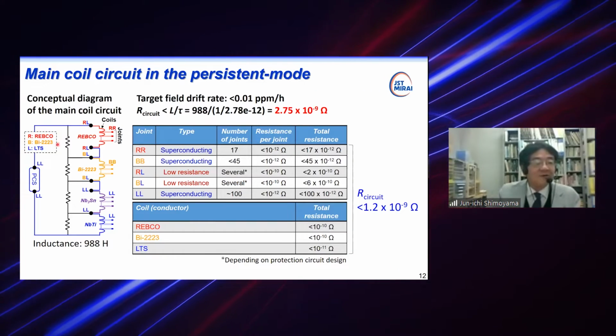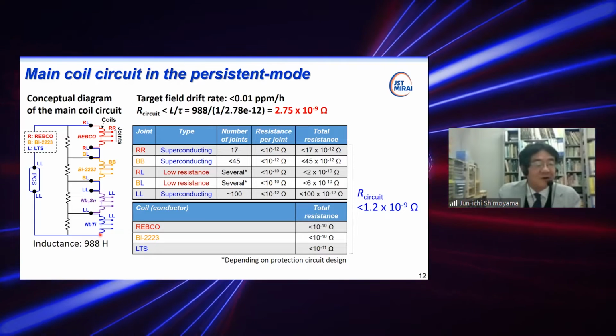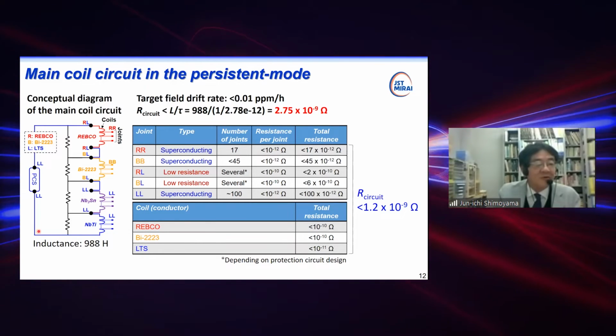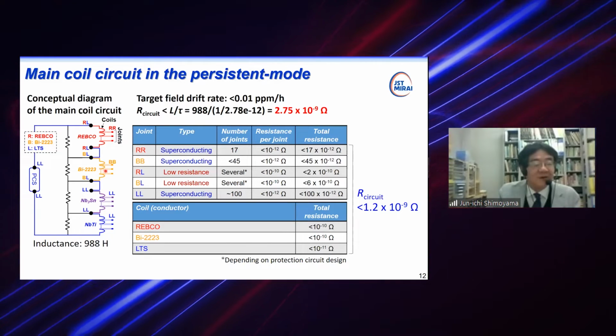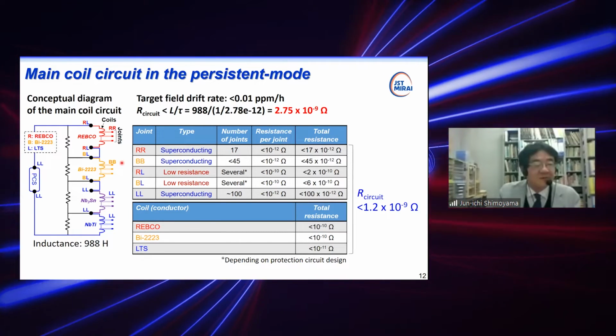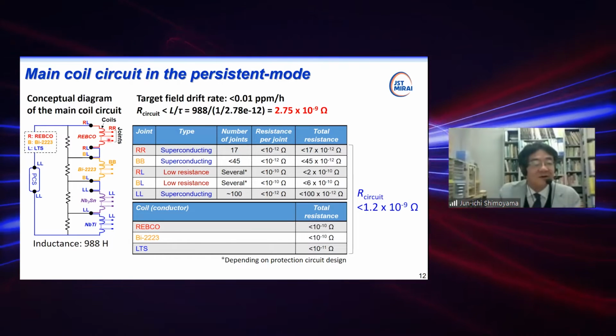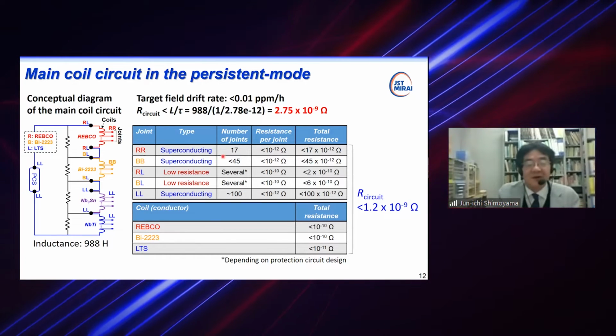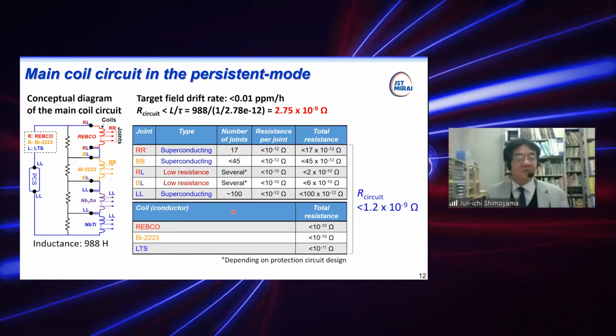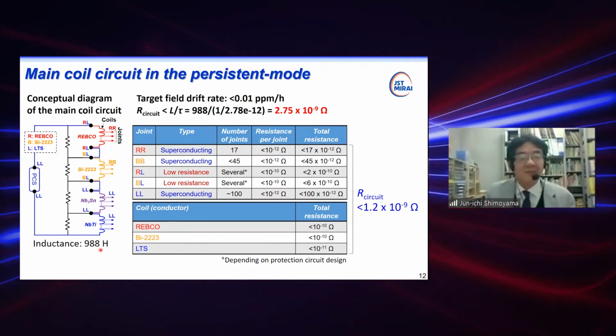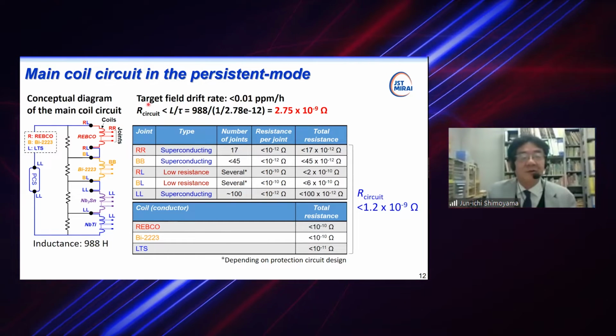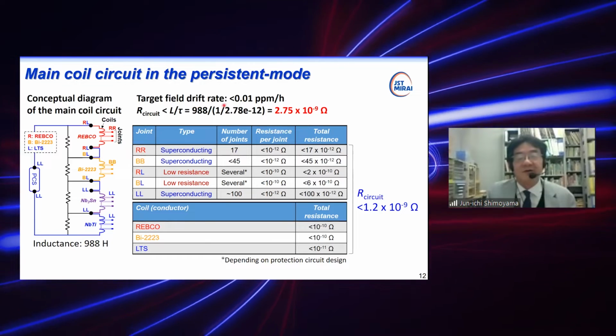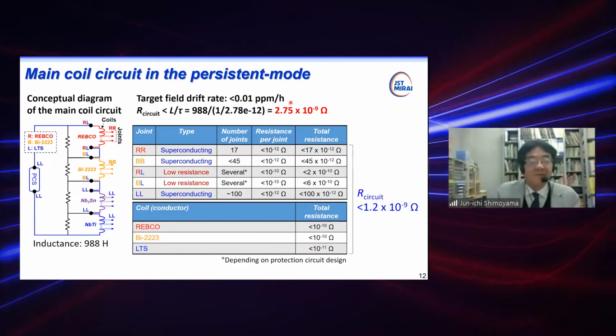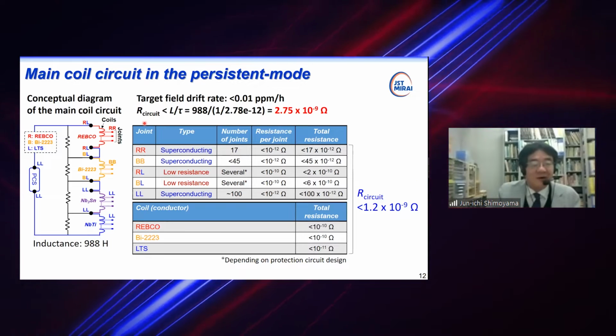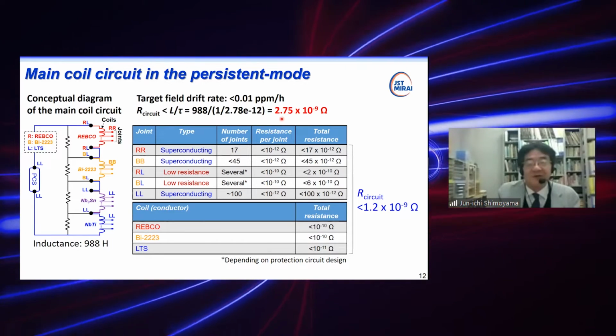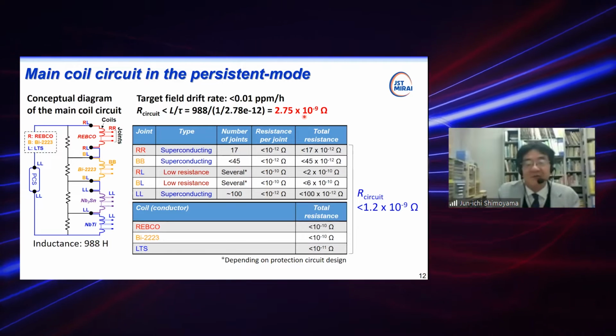If you see this circuit, these coils are connected in series, one loop as you see here, and there are many joints. Inside the Bi-2223 magnets, many joints here. Inside the REBCO coils, you see many joints here. The number is listed here again. Due to the very large self-inductance of the big magnet, if we want to achieve a very low field drift rate, less than 0.01 ppm per hour, it allows a relatively large circuit resistance. This is calculated to be 2.75 times 10 to the minus 9 ohms.